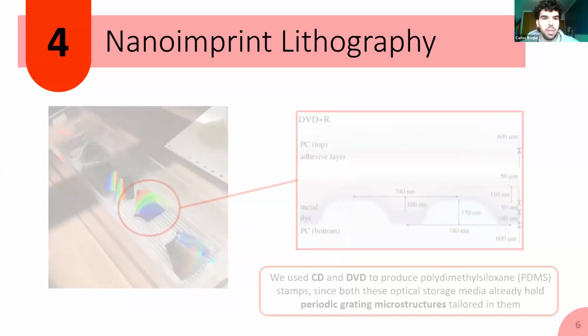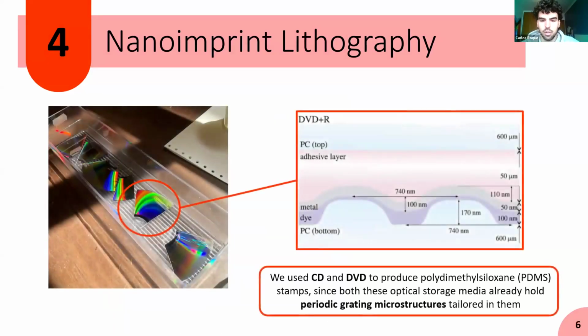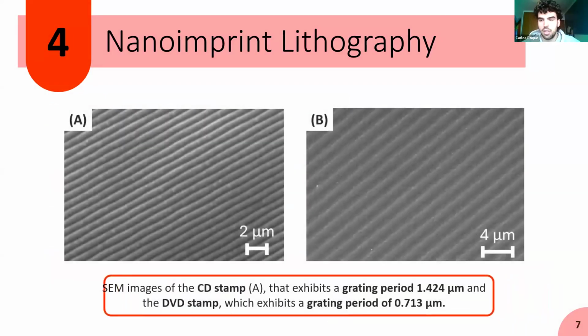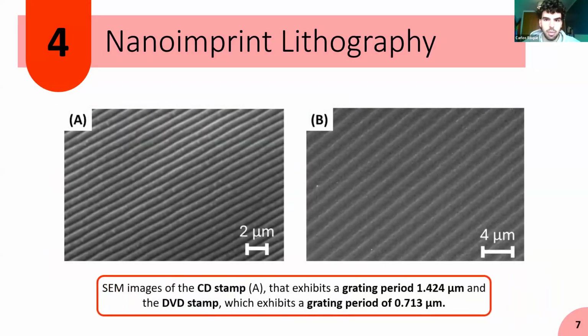We did that. Firstly, we fabricated the stamp. We use CDs and DVDs for that because they already hold the grating structures we want to pass, as you can see in the picture, and we use PDMS to produce this stamp. Then we passed on to the substrate we chose, which was PMMA. We chose to pass both with CDs and DVDs because they differ in periodicity, and by changing the periodicity, we can change the frequency of excitation of the plasmon. So we have different plasmon modes, and that's of interest to us.